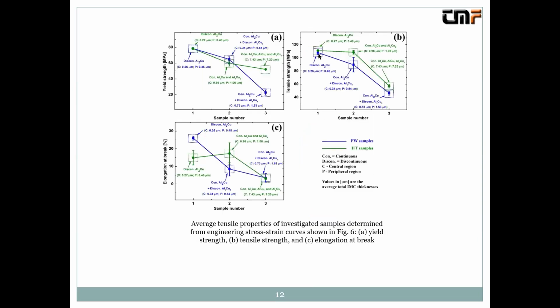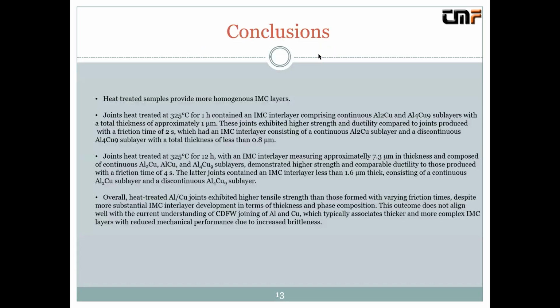In that manner, we can see that, let me show you, even for thicker intermetallic layers, we obtained higher strengths. That was probably the highest breakthrough of this paper. So if you thought that thicker layers provide poor mechanical properties, this is something wholly different, and provides us a lot of space to investigate the strength of the intermetallic layers and the strength of the sublayers, especially.